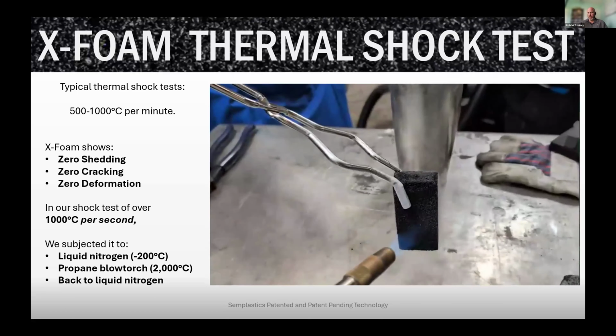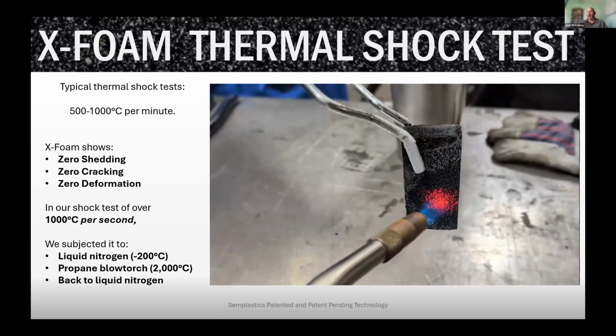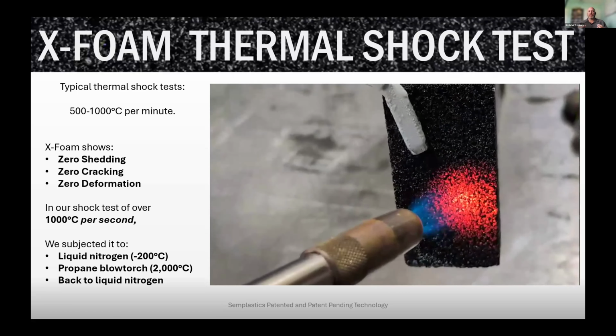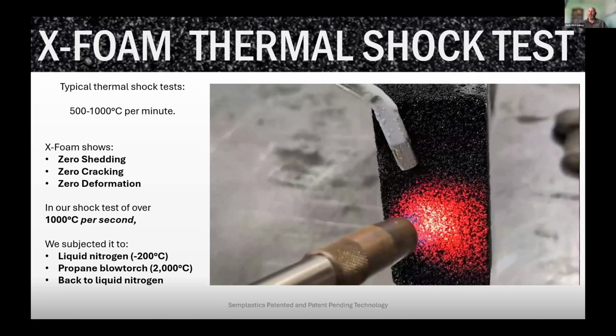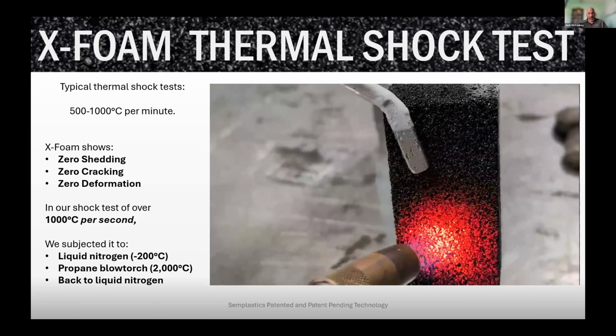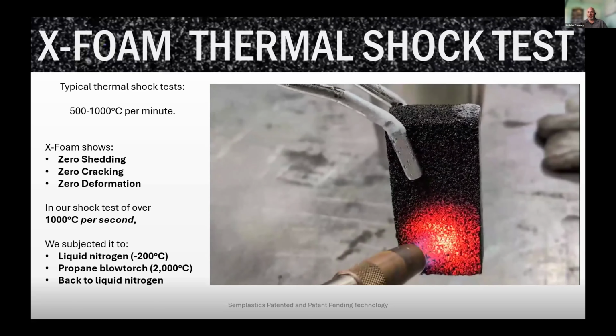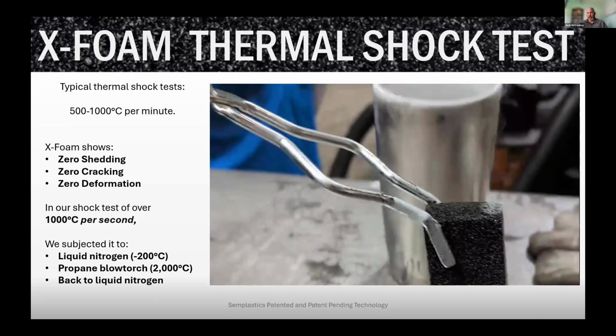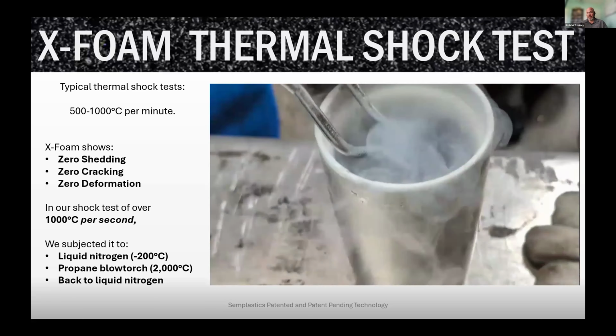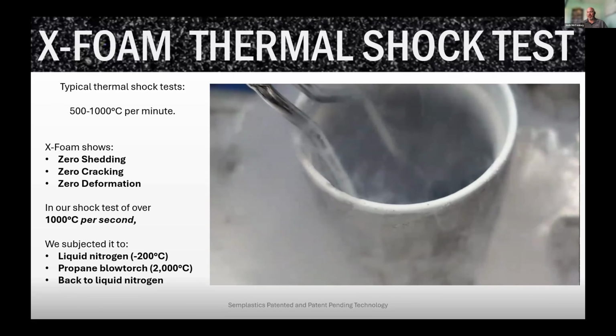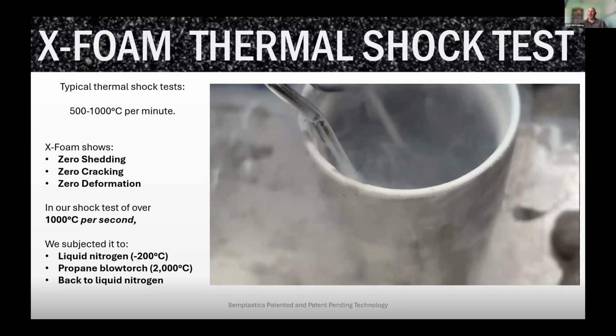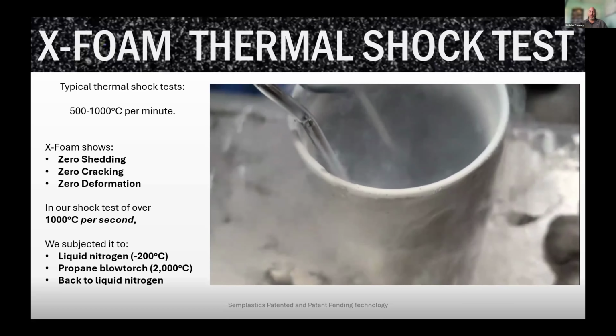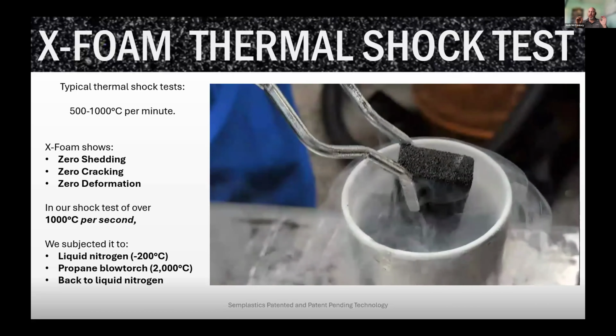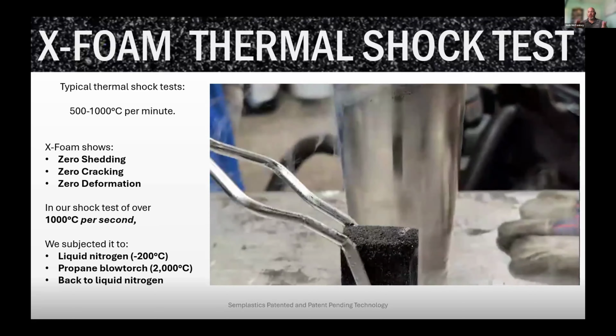Take it directly into the propane blowtorch until it's glowing. And this is a shock test that we're getting of over 1000 C, not per minute, which is considered a very extreme shock test, 1000 C per second. Then we dip it right back into the liquid nitrogen and let it sit there. Having taken this back out of that, we then have a situation where we have no cracks, no shedding.